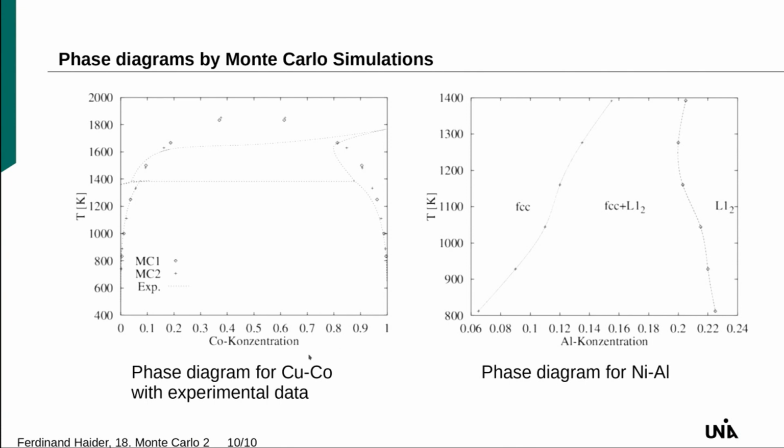It's different here for this case of copper cobalt, which does not show such an ordered phase, but it's a very simple precipitating system, binary system. It's not really simple. It has a peritectic here and a strange liquid solid region here. But the interesting part is here the solubility line on this side and the solubility line on this side.